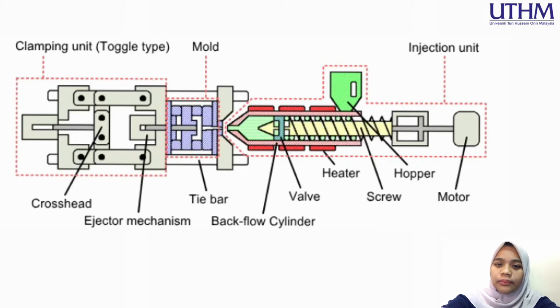The machine controls the moving speed of the screw, or the injection speed. On the other hand, it controls dwell pressure after molten plastic fills out the cavities. The position of change from speed control to pressure control is set at the point where either the screw position or the injection pressure reaches a certain fixed value.